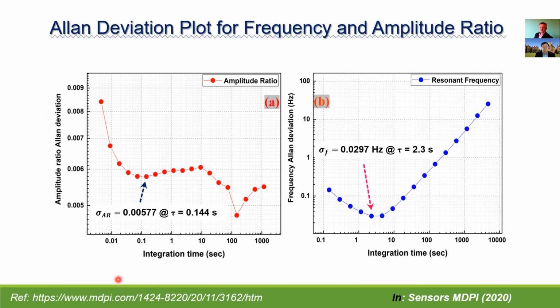Then the Allan deviation graph was plotted to compare the stability of the amplitude ratio and frequency output metrics by monitoring the shift in frequency and amplitude ratio for a 12-hour period. This is to monitor the variations in the amplitude ratio and frequency for long-term measurements. The point of using this Allan deviation plot is also to see what would be the minimum variations in the amplitude ratio and the frequency shift that can be obtained over time.